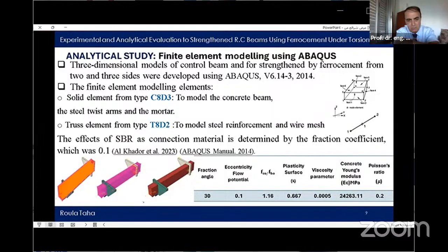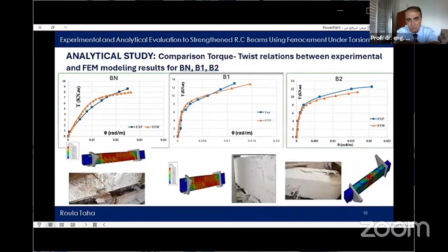The effect of SBR as connection material is determined by the fraction coefficient, which was set to 0.1. All the material properties matched those utilized in experiments. From the figures, we can notice that the failure pattern of the analytical model for the control beam was similar to the experimental results. Also, the formation and growth of the cracks are very similar.